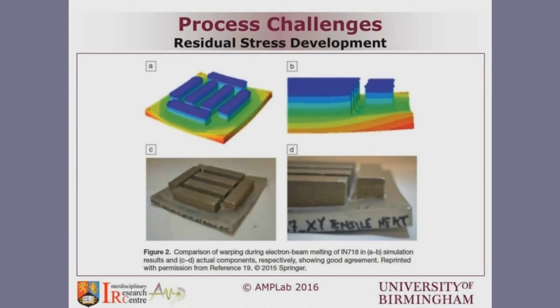As a result, you can change your process sequence or your process parameters, including the scanning strategy and how the heat input is applied, in order to reduce the stresses available in the material as you build in the as-built condition.